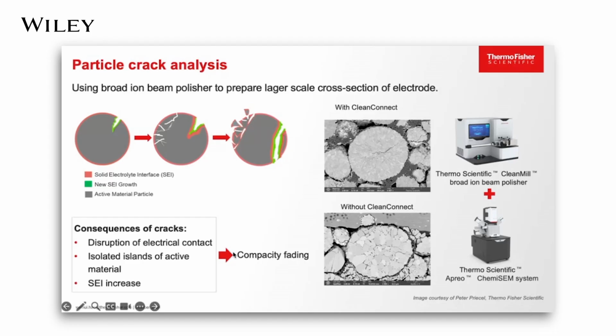And using Thermo Fisher CleanMill broad ion beam, we can get a nicely prepared large cross-section of cathode electrode without exposing to air due to its compatibility with our CleanConnect inert gas sample transfer system. And then using Thermo Fisher Apreo ChemiSEM for imaging the cross-section at a really excellent fast imaging capability. And finally, we always want to know how many cracks are across the cross-section of the electrode.